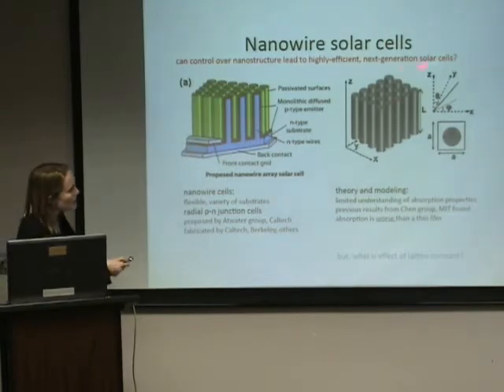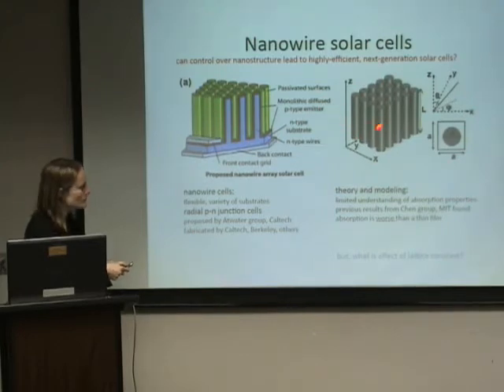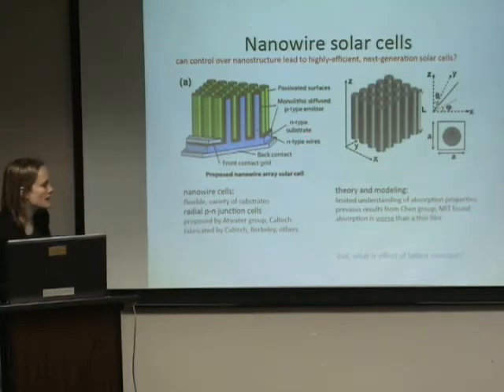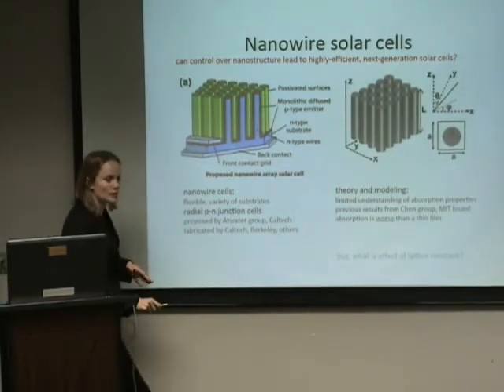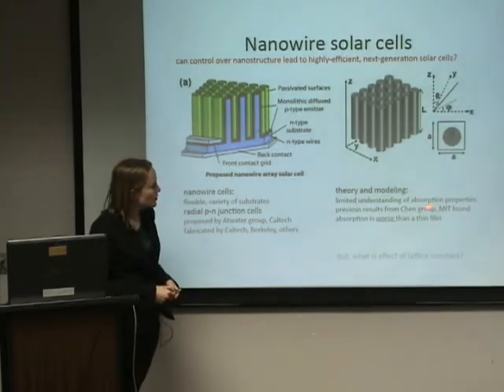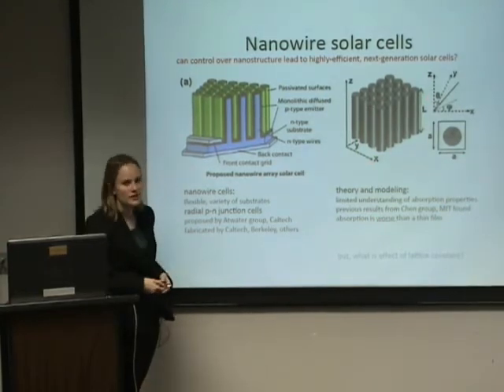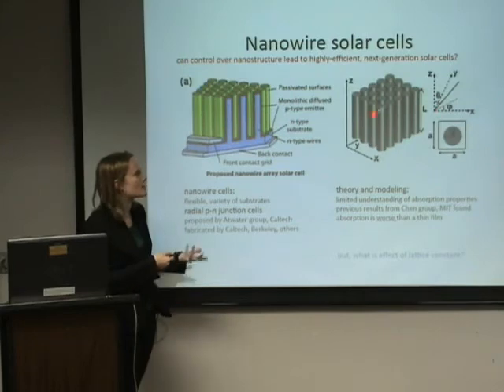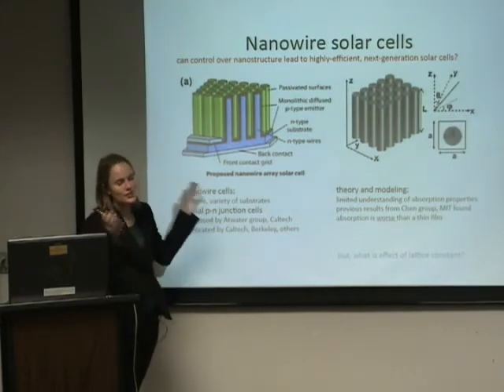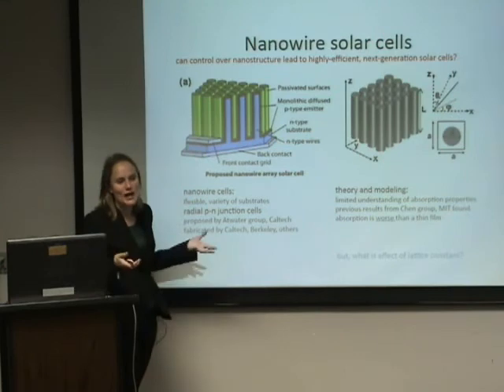So we'll study a model that looks like this. We're considering these nanowires where, like the proposals, they are lined vertically, and they form a regular array. And actually, the absorption properties of these arrays has been quite limited. We found one previous paper from the literature, which was from a group at MIT. And they modeled certain absorption properties here, but they found if you use a structure like this, you do way worse than if you just didn't have any structure at all. So just use a thin film with the same height, and you'll have a higher absorption.